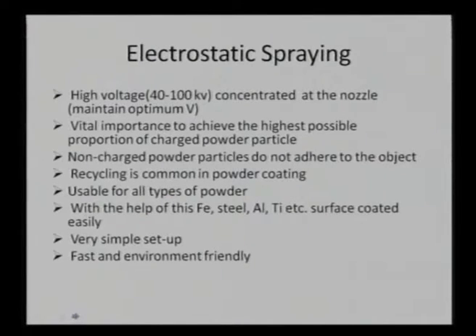In this process, we will focus on what electrostatic spraying is and how it has been utilized to create a biocomposite coating. In electrostatic spraying, we apply a very high voltage, on the order of 40 to 100 kV, which is concentrated at the nozzle and maintained at an optimum voltage. The vital component here is that we can attain highly charged powder particles. So, the powder itself has to be much more insulating in nature, so that charge can be created on the powder particle when it is passing through the nozzle, which is being maintained at a certain high voltage.